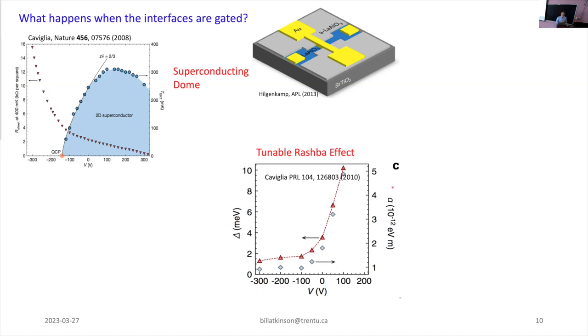So if the red data here is the spin splitting at the Fermi surface, you can see, or I can see anyway, that it goes from about 1 millielectron volt at low gate voltages up to about 10 millielectron volts. So that's a full order of magnitude as you sweep the gate voltage.